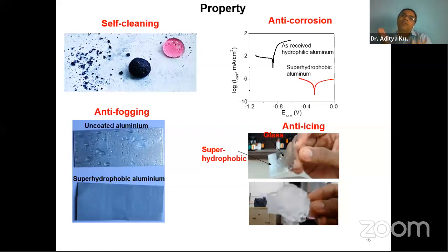It will always repel your seawater, and it does not let your material or your aluminum or metal surface get wet. Once it does not wet, you can't have the corrosion, because in corrosion you need to have water contact, moisture in contact. So here we have measured scientifically, and we found super hydrophobic surfaces have high corrosion resistance.